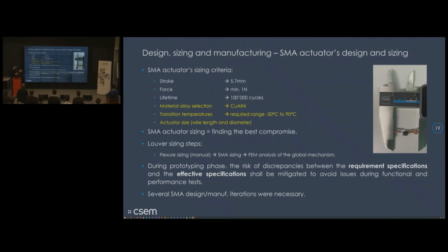In general, during the prototyping phase, the risk of discrepancies between the requirement and the effective specification should be mitigated to avoid problems during SMA integration in the mechanism, for example, and the performance tests. What I mean is, an SMA prototype cannot match 100% with the specification that you need for a prototype. In our case, we had to size and manufacture several iterations to obtain more or less what we wanted.